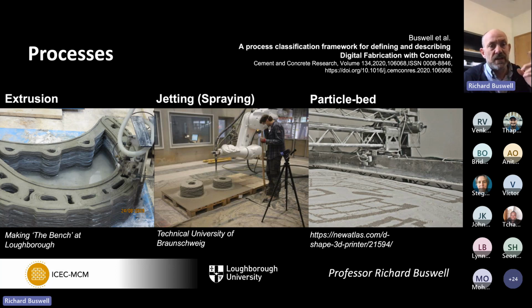There's an increased use, obviously, with extrusion, not just mortars, which have small aggregates, but starting to use larger extrusions with bigger aggregates in, because obviously one of the snags is that the extrusion process means you have quite cement-rich materials, perhaps with twice the amount of carbon emissions associated with it as conventional concretes. So you want to minimise that. And one way of doing so is to actually increase the aggregates so that you can minimise the paste amount. So in a lot of volume applications, there are more concretes being used.